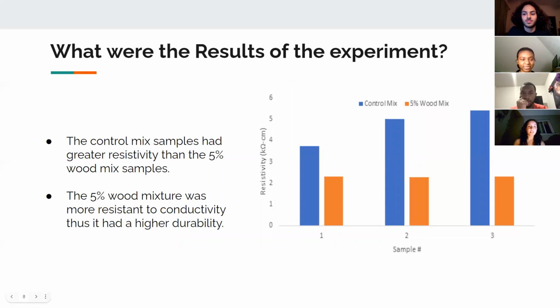Yes, I can. So for the results of the experiment, as you can see in the figure on the right, the control mix samples had a greater resistivity than the 5% wood mix samples. This alludes to that the 5% wood mixture was more resistant to conductivity, and therefore that alluded to as well that it had a higher durability.